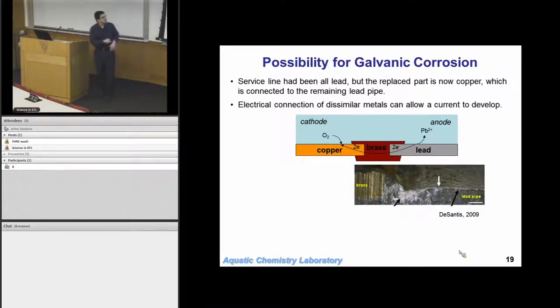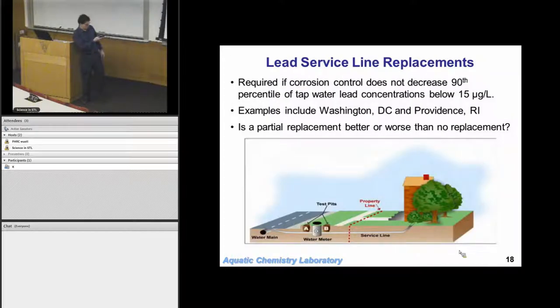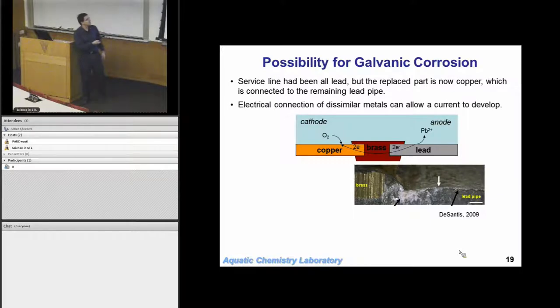And so you would have places where you'd have a lead pipe connected to a copper pipe and coupled together with a brass coupling. They're nice, they don't leak, the people who are doing these know how to work with these materials, except those of you who know a little bit of electrochemistry here, we say, well, copper and lead are different metals. They are now electrically connected. I have an electrolyte out here. That's a battery. Okay. So there's something called galvanic corrosion, where the lead becomes a sacrificial anode relative to the copper. So the lead is getting oxidized based on reduction reactions happening on the copper. So putting the lead with the copper could actually make the lead release worse.